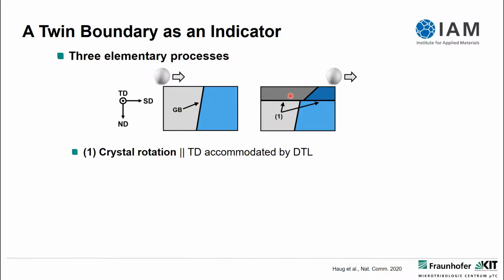That's also something we had seen previously, hinting toward the character of the dislocation trace line as a small angle tilt boundary. So this is the first process, which is also something we would see even without the witness of the twin boundary. The second one is what we call simple shear. We shear the area of material above the dislocation trace line, in this case above the lower dislocation trace line in sliding direction, like a deck of cards, basically.